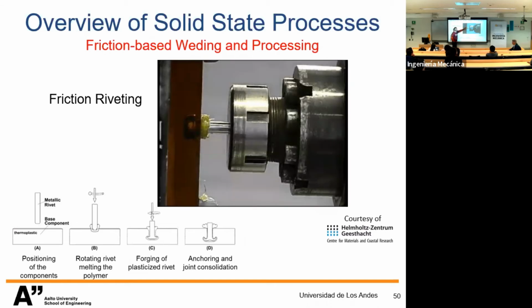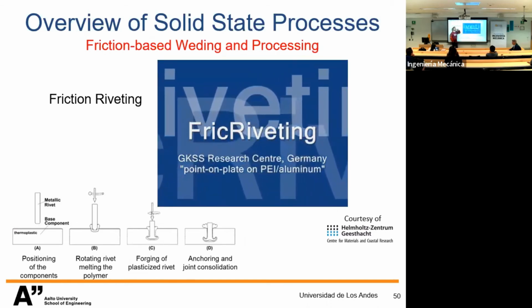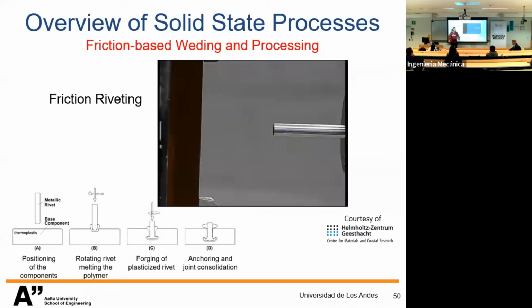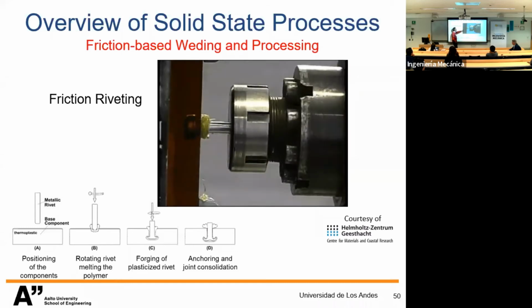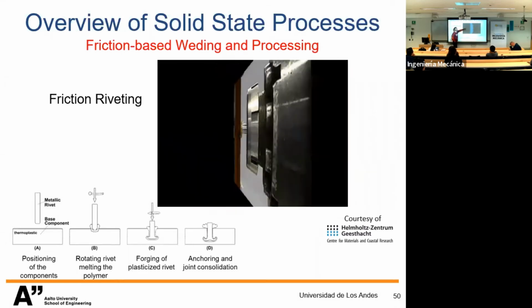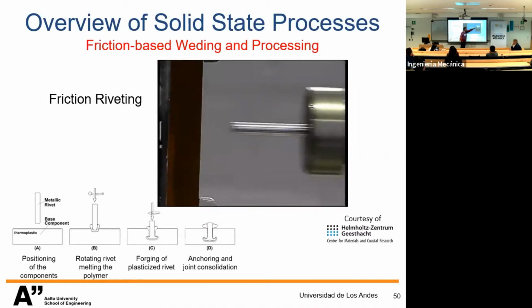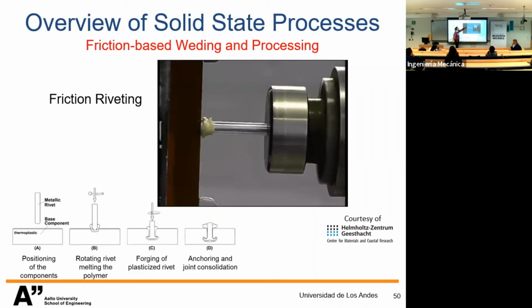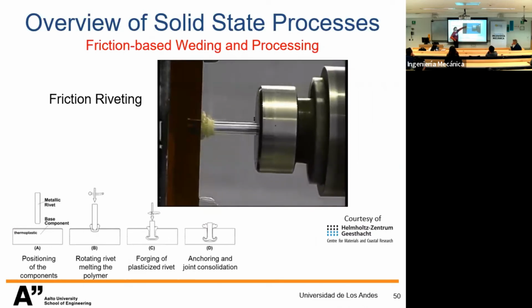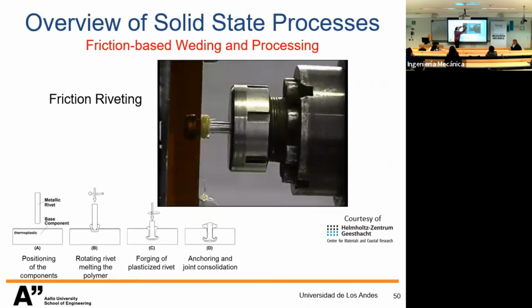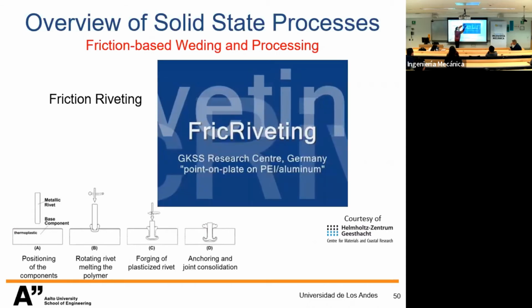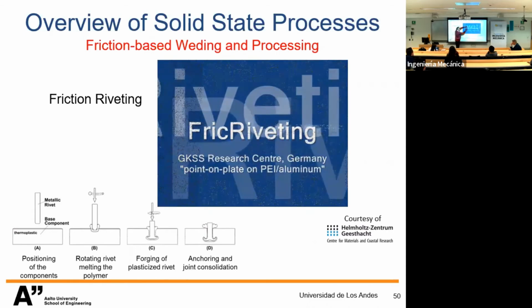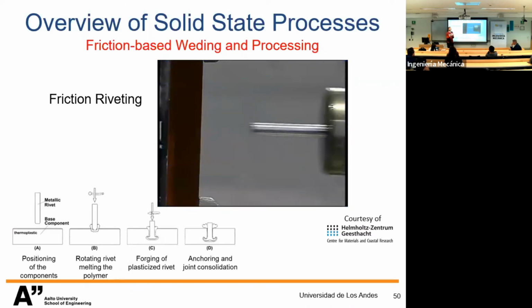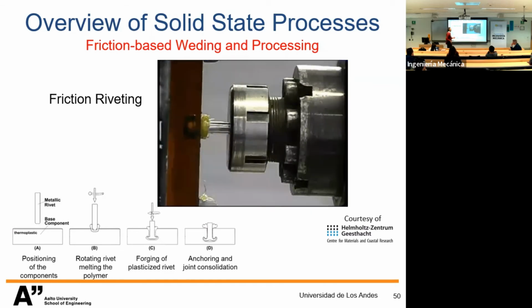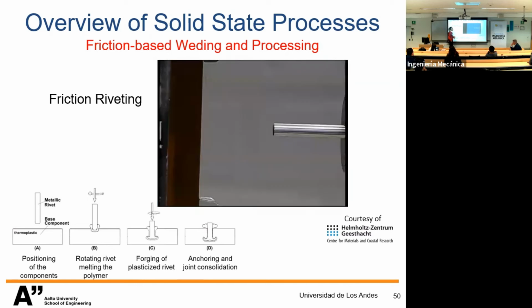So the issue is the game of physical conditions. The metal is hard, but has high thermal conductivity. The polymer is soft, but has low thermal conductivity. So you start to have heat dissipation at the interface between the materials, and the heat flows through the aluminum. As the heat flows, the strength comes down. But in the polymer, because it has low heat conductivity, around the processed zone the temperature is essentially room temperature. So there is a moment where the strength of the polymer becomes higher than the strength of the zone being processed by the metal. This is a multi-physical gain, and a complete change of paradigm of the forming part. Amazing to understand the mechanism.